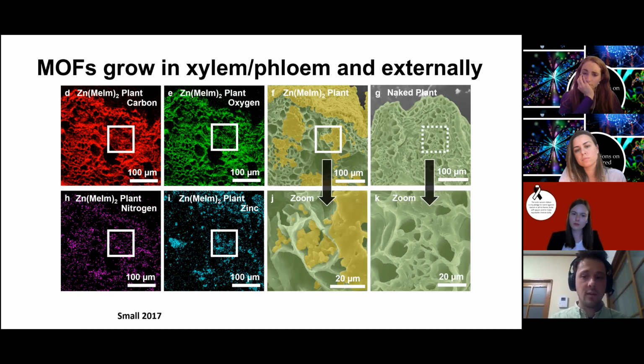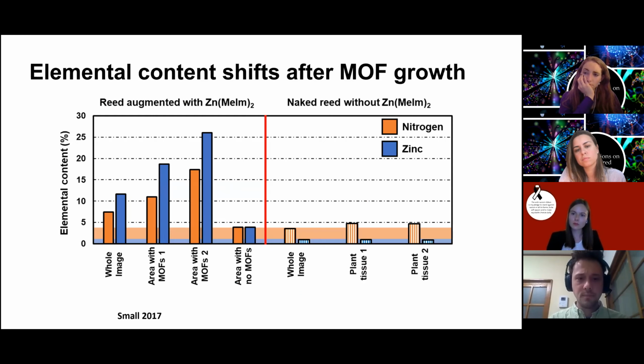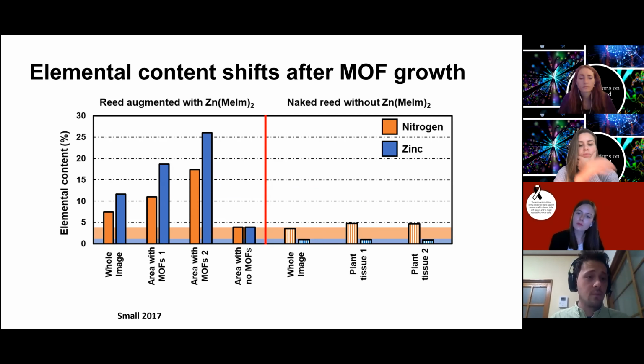The outside is very, very smooth. The inside is very smooth. We don't see these crystalline particles. So we did some more elemental analysis, and on the left-hand side, these are the plants that have the MOFs in them. You can see that the nitrogen and zinc composition is incredibly high compared to native plants, sometimes above 10, 20%. This is interesting in terms of showing how much of the material is actually MOF, but also, of course, nitrogen can be very useful for plant growth.